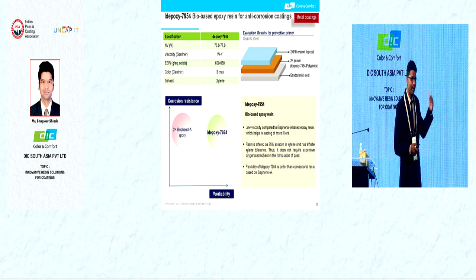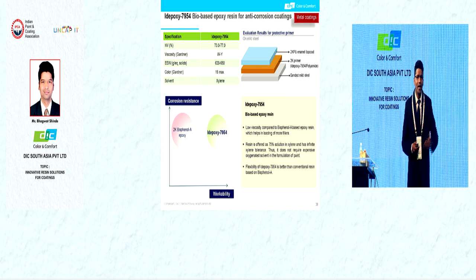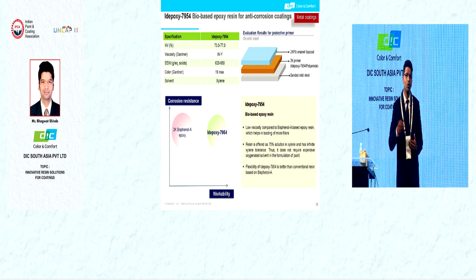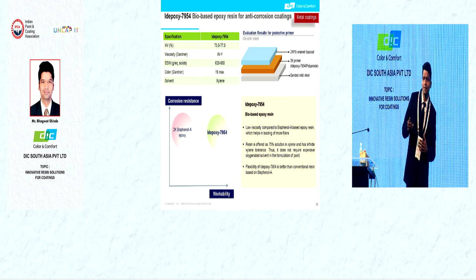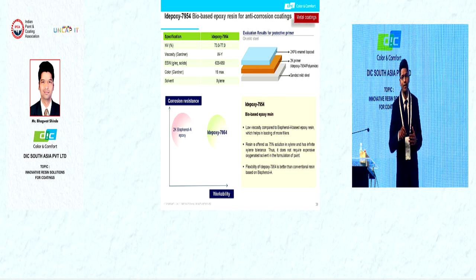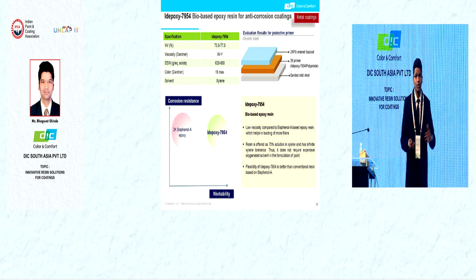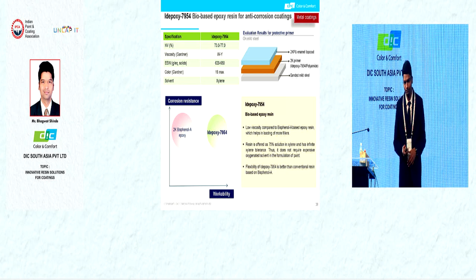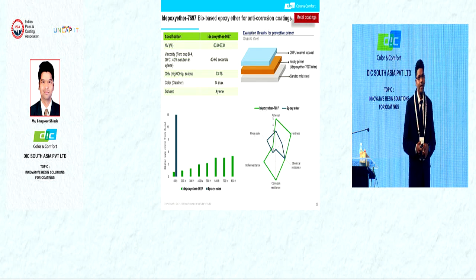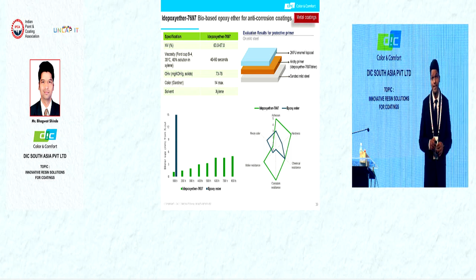And due to the higher equivalent weight, you require a minimum or lower quantity of hardener. So the resin and hardener quantity, or the resin and hardener mix price, will be lower. So next one is the ID Epoxy Ether 7697. This is the bio-based epoxy ether.